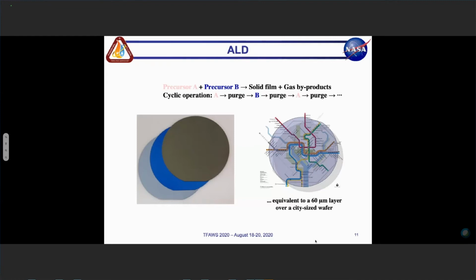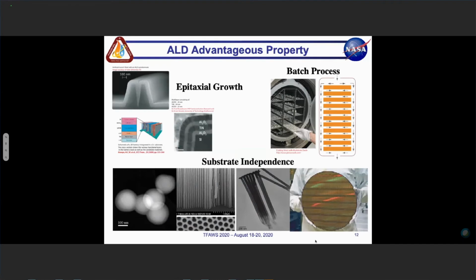So if we were to take a silicon wafer and expand it to the size of the DC metropolitan area, pretty much what we would see is a uniformity of about 60 microns across this wafer. So the uniformity is spectacular for this type of manufacturing process.